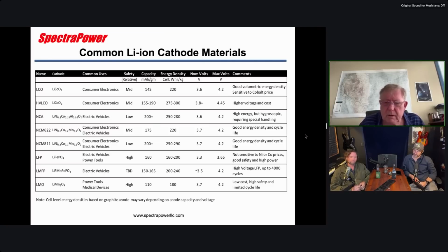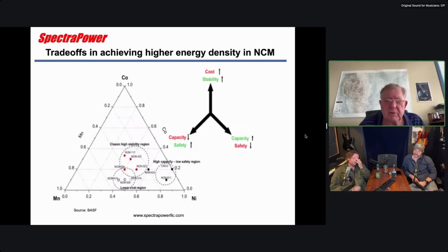So I was just going to say, this is nickel, cobalt, manganese, and this is cobalt, this is manganese, nickel, and these are the percentages that you can put in a cell. It just kind of shows the trade-offs you're making. So as you go to more cobalt system, chemically it's a little bit more stable, but it's expensive because of cobalt. When you go to more manganese, the capacity goes way down and the safety goes way up.